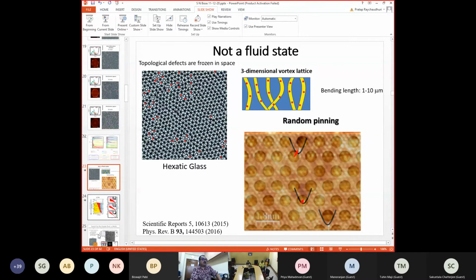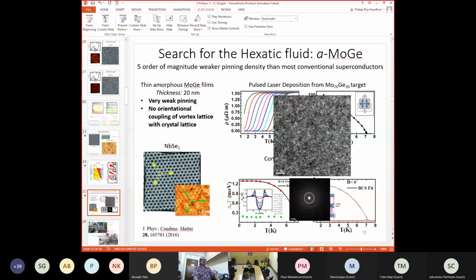So with this knowledge, we got an idea of what the constraints are if we have to see a hexatic vortex fluid. One thing is that we need to be in systems that are extremely low pinning, so very uniform. The second thing that we realized is that a crystalline superconductor is very bad for our search, and that is because in niobium diselenide we performed these experiments.